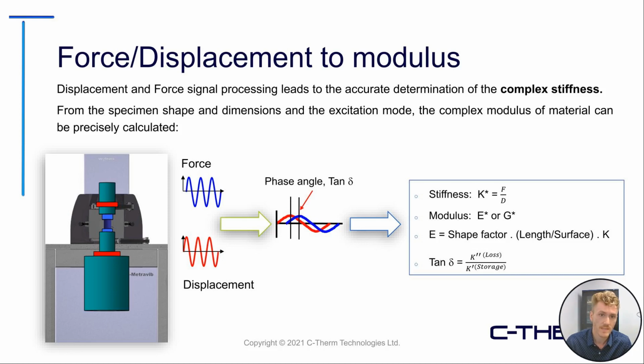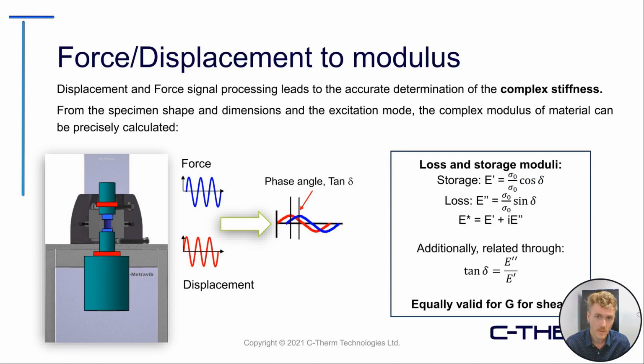Additionally, the force and displacement which are measured can also be manipulated with a phase difference to give tan delta. Tan delta is equal to the loss modulus over the storage modulus. Loss modulus is the dampening effect of the complex modulus. It's usually proportional to some of the intrinsic friction within the material, leading to heat loss. And the storage modulus is equal to the ability for the material to store this energy and release it in an elastic sense. Additionally, these are related for shear as well through these equations right here.